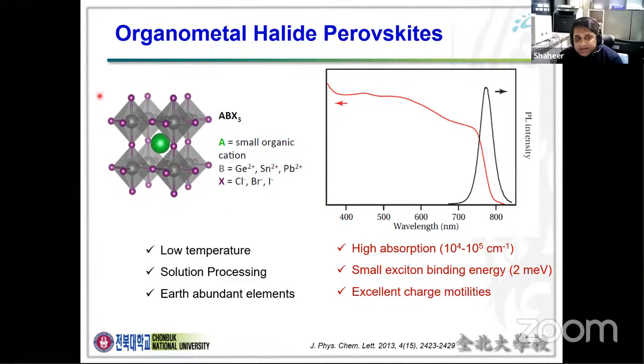And the good thing about this kind of perovskite material is that it shows a high absorption coefficient, which is like 10^4 to 10^5 per centimeter, and it has a small exciton binding energy, which is 2 milli electron volt, which is highly helpful for the separation of excitons. Of course, it also shows very good charge mobility, so the charge injection is faster than in the dye-sensitized solar cell. These kinds of perovskite materials we can easily manufacture at low temperature, using a solution process.